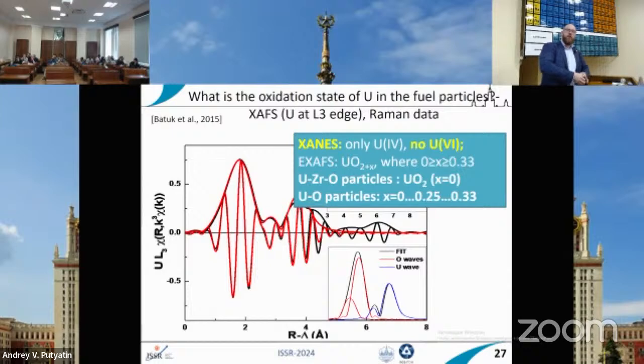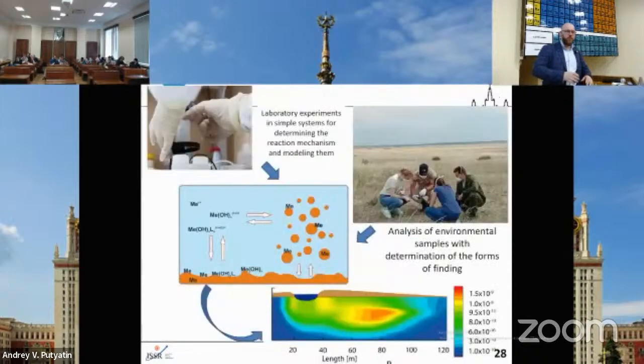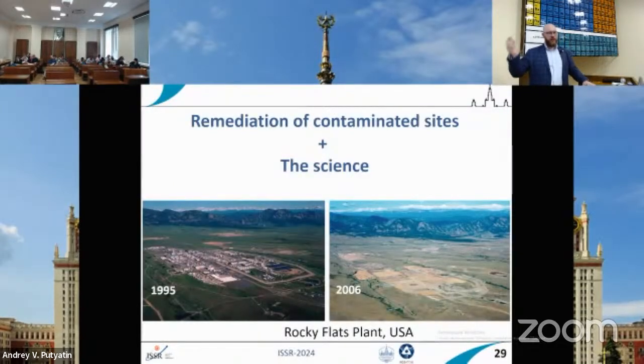After all these years, this investigation was in 2015, almost 30 years after the Chernobyl accident, but these fuel particles are still in the form of tetravalent uranium with some non-stoichiometry, and they are still very stable. So I showed you already this picture about the determination of these thermodynamic parameters in the lab and their verification in real samples.